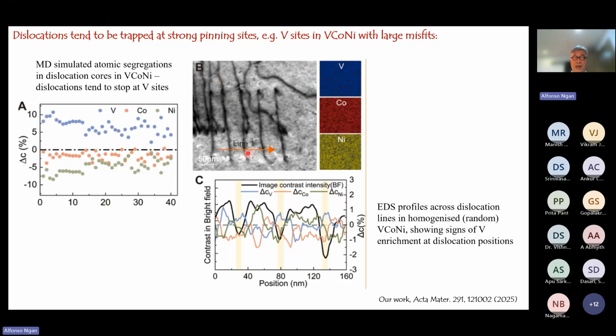And B and C would be experimental results. So here we have a few dislocations. And as we do a line scan across them, whenever you detect the chemistry at a dislocation site, you'll see a little bump in the vanadium content. So that more or less confirms the MD-MC result.